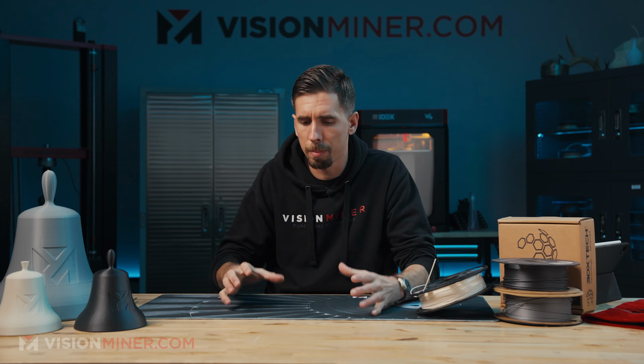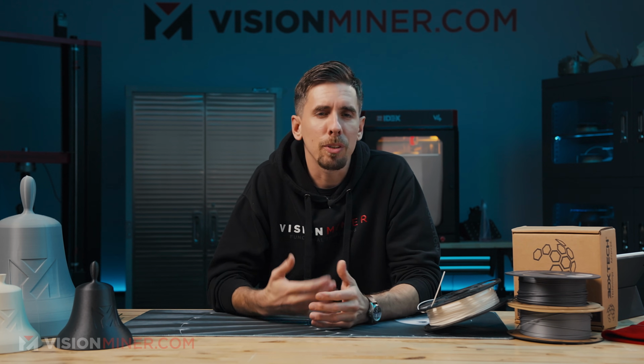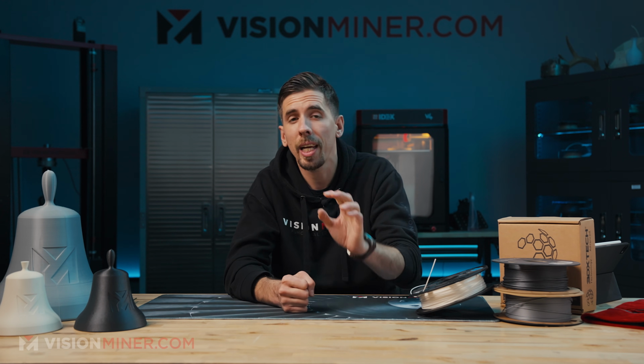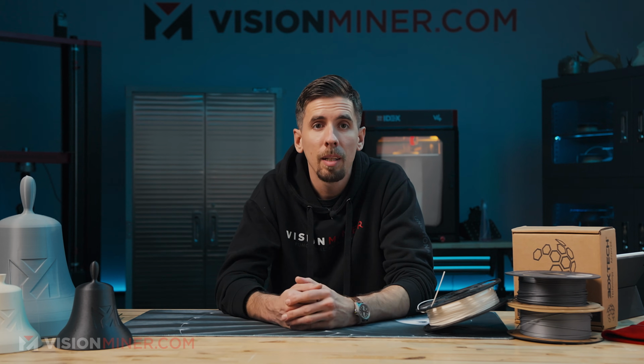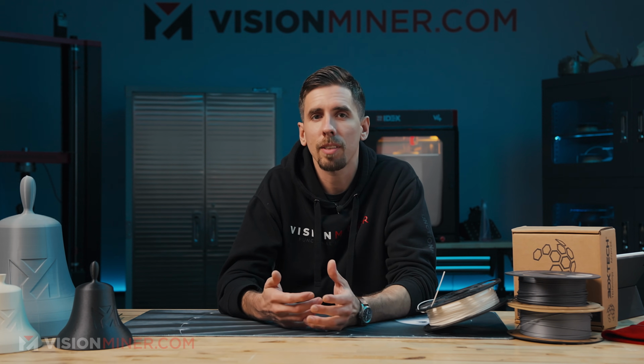Now, you might be saying, oh, I can print this on my Bambu or something like that. And it's like, well, yeah, you can extrude it and you can make a geometrically sound part, but most of the time you're not actually getting the full performance. If you print PPS in open air without a heated chamber and proper thermal control, then you will get a part out, but it won't give you the true performance of that semi-crystalline structure within the part. Now you can anneal the part, and that'll help a lot, but often annealing after the fact costs you all the dimensional accuracy and your part basically warps out of shape. Now, high-end engineering polymers like this, they demand process discipline. When you give them that, then the results are usually incredible.